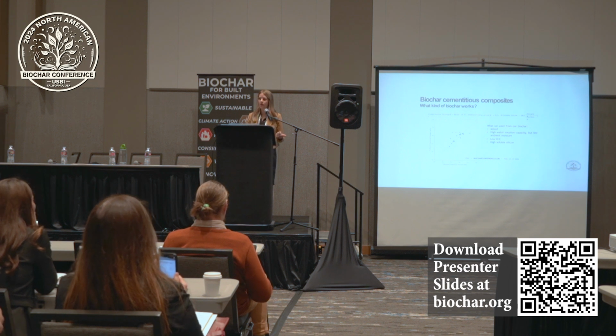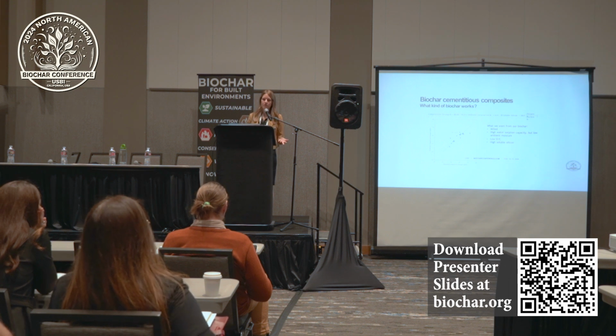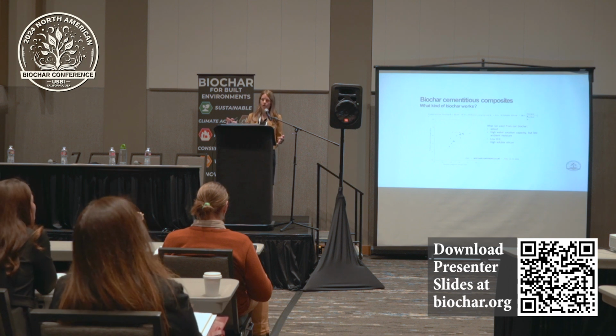So those are our three variables that we need to control. Soluble silicon, I mentioned that already. That's predictive of the pozzolanic reaction, so that one makes sense and why we want the most soluble silicon we can. Oxygen to carbon ratio, that's well known to all of you. And then it's the ambient saturation percentage. We're defining that as basically the percentage of the total absorption capacity of the biochar that's already occupied by water under ambient conditions. So basically it's giving a measure of how much of the biochar absorption capacity is already occupied and how much is left for additional reactions in the cement system.